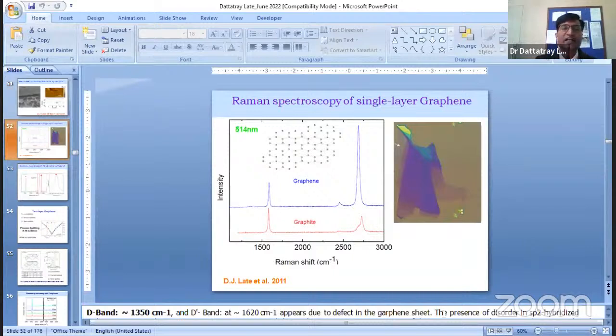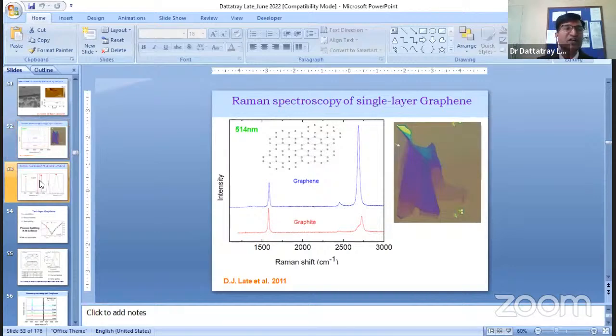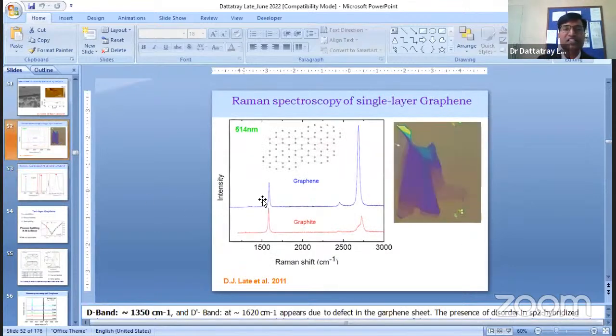You see, in this typical Raman spectrum of single-layer graphene and bulk graphite, this is the G peak, which arises because of the stretching of the carbon-carbon bond, and this is the 2D peak, which arises again from laser frequency dependence, and is actually used to monitor how many layers are present in your particular grown or transferred graphene layers. One of the parameters is the intensity of this G band and 2D band. If the intensity of the 2D band is 2 to 3 times that of the G band, then you can say that this is a monolayer of graphene.